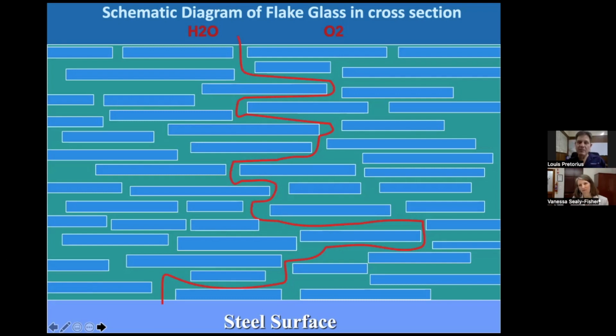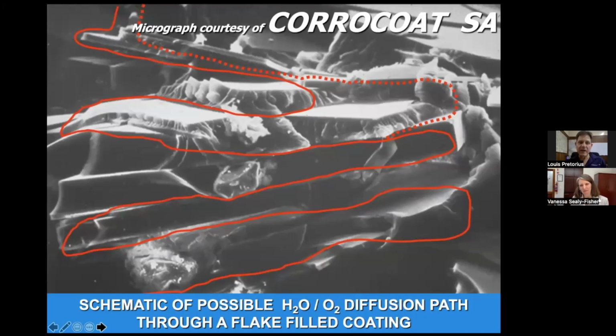Quite often we compare the performance of the resin system without flake at a given thickness to the diffusion or the permeation resistance of the resin system with flakes. And then once you compare those two, you'll see that there's orders of magnitude improvement in permeation resistance or slowing down of the rates of diffusion. So what we're looking at there is some flake-filled coating, and just a little bit of background on how we make that. We have the privilege of owning 2 electron microscopes. So what you do is you take the coating and you freeze it with liquid nitrogen, and then you shatter it, and then you mount it like that without polishing it. That's how we get these photographs.